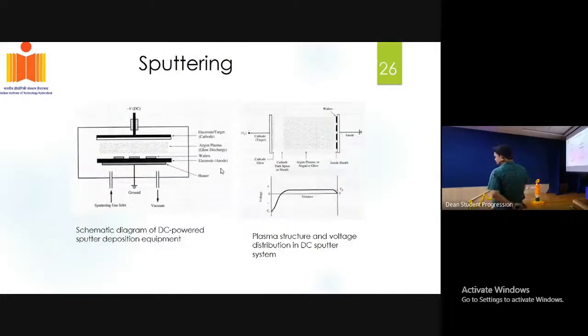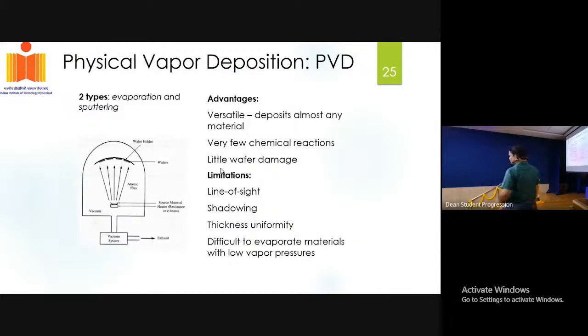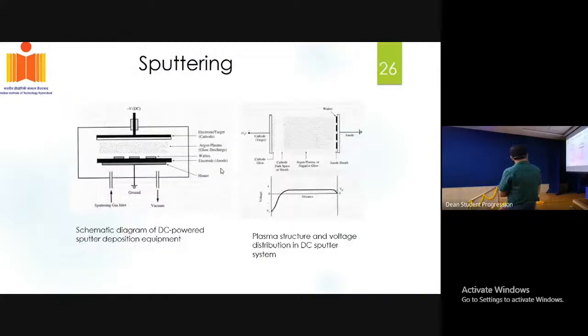And apart from that, the most prominent physical vapor deposition technique is sputtering. In the case of thermal evaporation, you physically evaporate the material. You melt the material and deposit it. In the case of sputtering, you don't do that. You have to create argon plasma within the chamber. That means you first fill your entire chamber with argon gas and apply a high potential difference between the cathode and anode. The argon atom will split into an argon ion and an electron. These electrons will interact with other argon atoms. It's basically a cascading process that gives you the argon plasma. Now, the argon ions will be moving very fast.